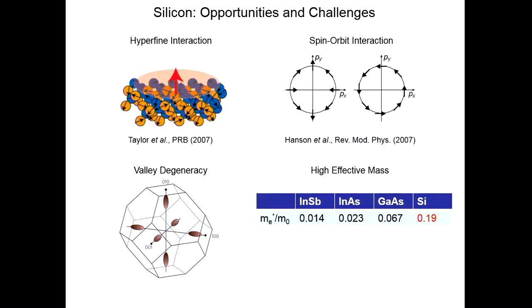One big difference between III-V and silicon is that there's a valley degree of freedom in silicon that we need to take into account. Another practical thing that's important when you're making a quantum device is that small effective mass is your friend. Early experiments in indium arsenide, indium antimonide, materials with a really small effective mass, give you nice quantum energy scales, right? Because everything goes like 1 over mass. And so in silicon, the effective mass is significantly larger than in gallium arsenide or indium arsenide. And what that means is if you want to make a quantum device and see orbital excited state energies that are reasonable, you need to make a really small quantum dot, a very small box for the electron to sit in.